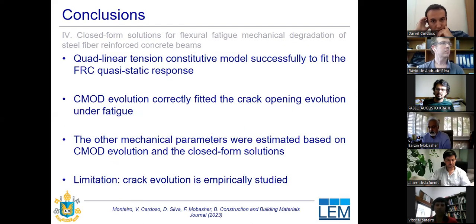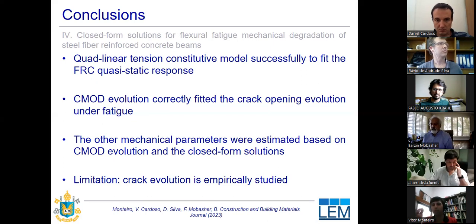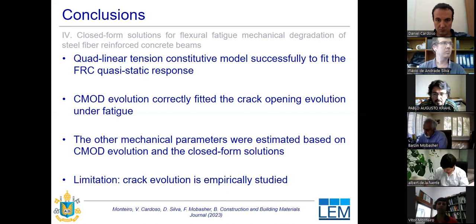So as a conclusion for this section, we have that the quad linear constitutive model was a good fit for the quasi-static results. So the quad linear tension constitutive model was successfully used in this analysis. The proposed empirical equation for CMOD also presented a correct fit for the CMOD under fatigue, and the closed form solutions were used to estimate the other mechanical parameters' evolution along the fatigue.